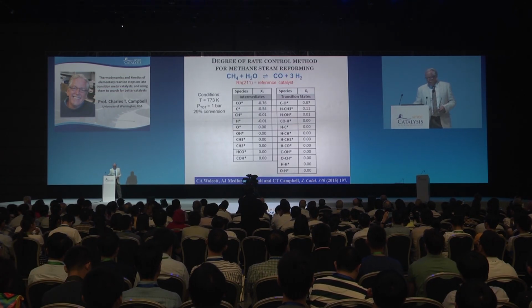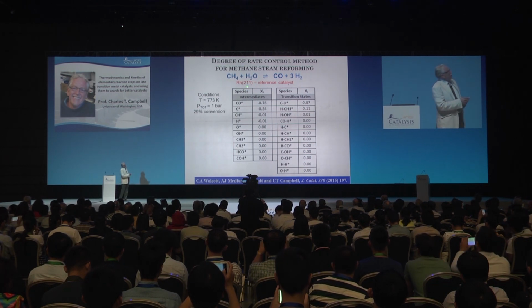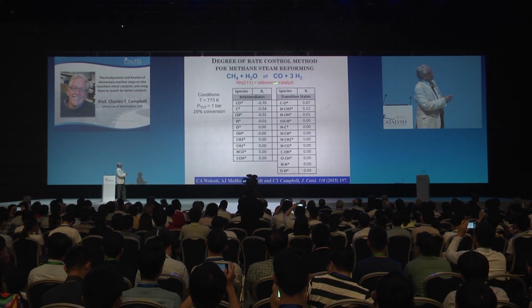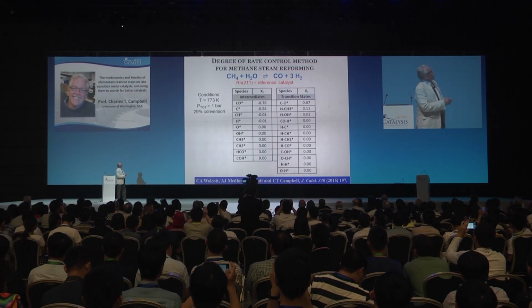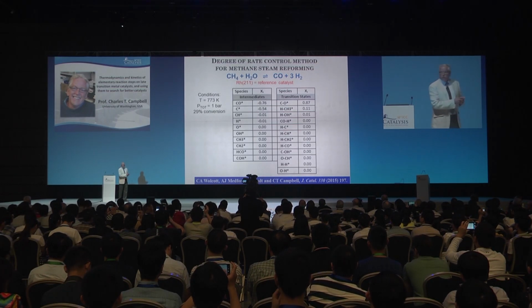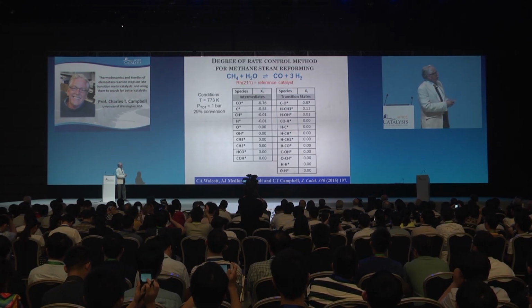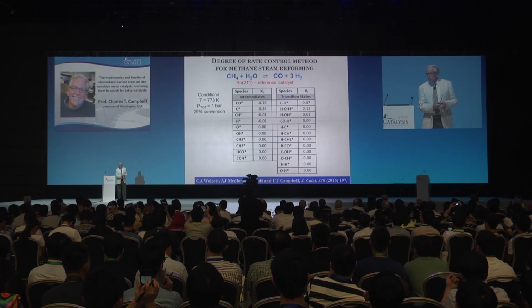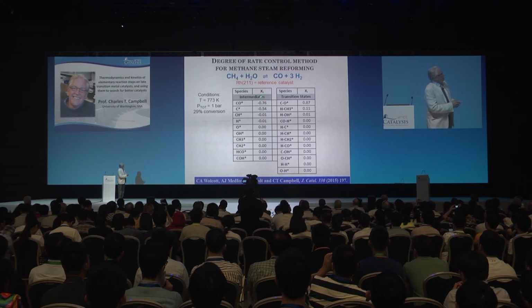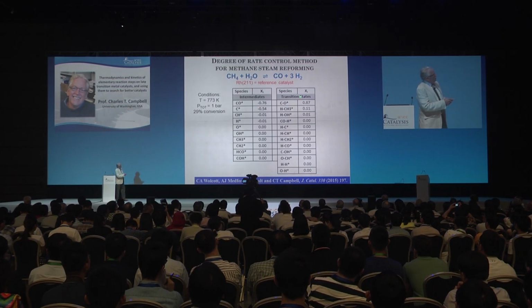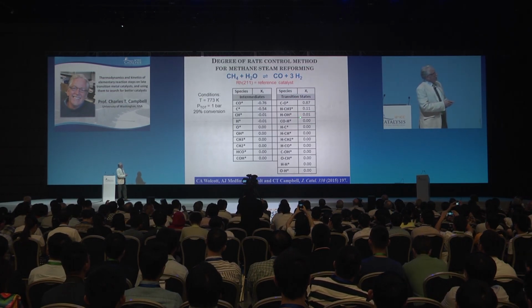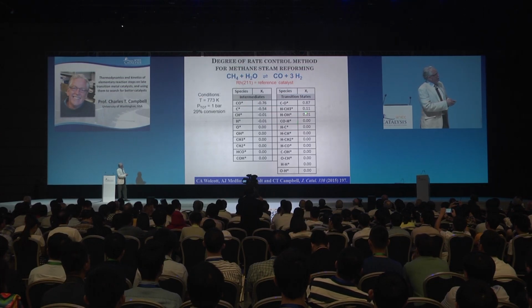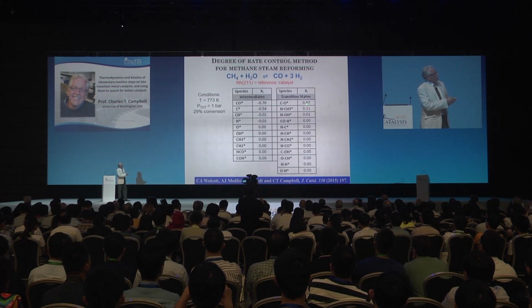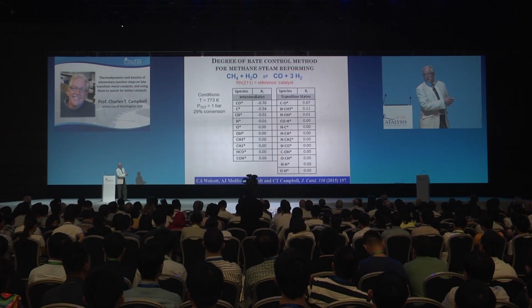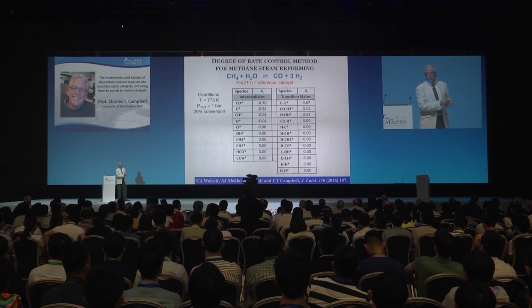So here's an example of a solved microkinetic model for the methane steam reforming reaction at these conditions using energetics from density functional theory for rhodium-211, in collaboration with theorists from Jens Norskov's organization. And these are the degrees of rate control, and these are for the transition states, that is for the elementary steps that have these transition states. And you can see that the degree of rate control is essentially 0 for all of the elementary steps except 2. And this is almost the rate determining step, but this has a substantial degree of rate control.